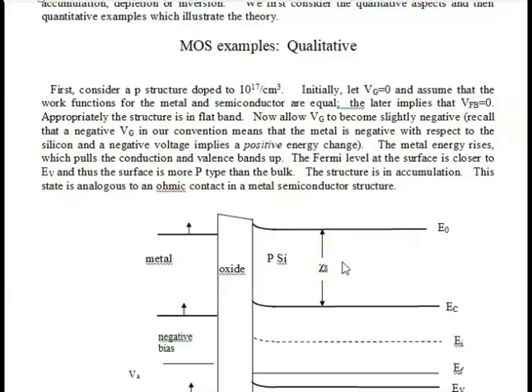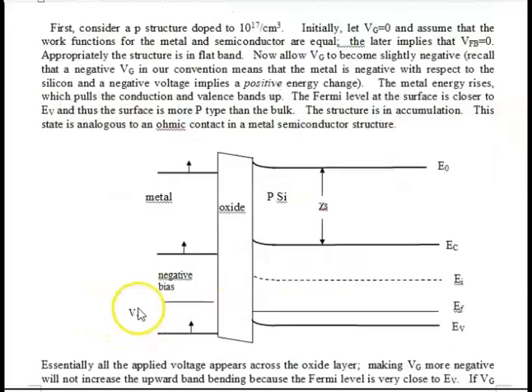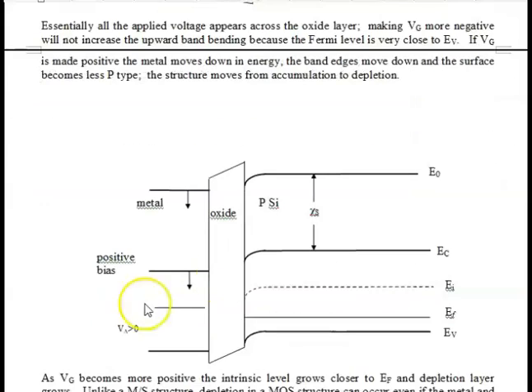So now we're going to flip the bias on the metal, and we're going to put a positive bias on the metal. And then we get the P bands bending down, and the oxide also having a positive slope. Notice again that the slope on the oxide is the same as the slope on the silicon, except the value of the slope is somewhat less in the oxide. And here we're pushing the metal down with a positive voltage. And we see from the diagram that this particular energy band diagram shows a structure in depletion.